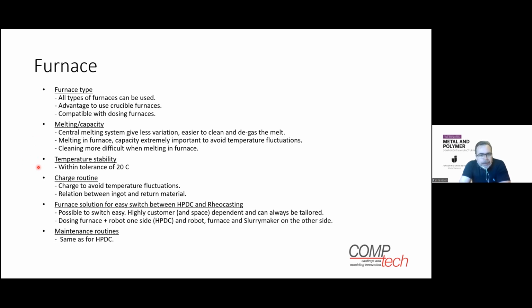Regarding temperature stability, we have shown that with a tolerance of 20 degrees we are able to keep a very stable process and slurry. So people who think that it's very important to keep the metal at exactly the same degree, or very low, that's not really true. We have a width of around 20 degrees.